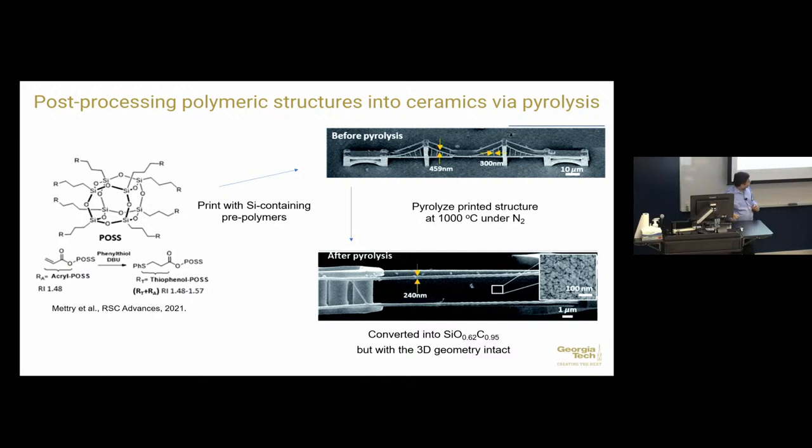So what is key in here is it's not just converting this chemical composition, but it's also holding the geometry while this conversion happens. That is something that enables us to actually print these ceramic structures additively, where you would see a linear shrinkage when some material is lost, but the relative shapes would still be the same. So you can still make these complex 3D structures in ceramics by printing something which is larger and has a polymer reactive component, so it polymerizes.